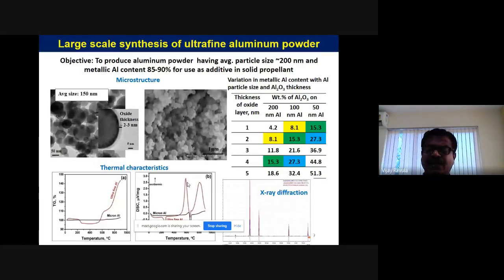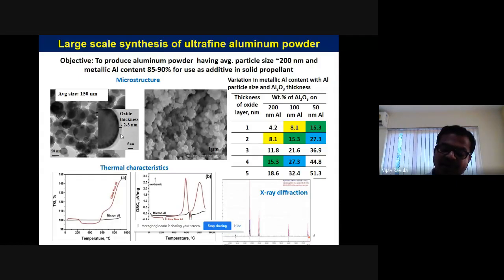So in order to improve the shelf life of the material, what we have done is, on the particles, we grew an oxide layer. It's very thin. The beauty of aluminum is, once an alumina layer forms, it doesn't allow the oxygen to diffuse further. It acts as a barrier for oxygen going into the material. But the problem is, if the thickness is more, they don't burn. Alumina itself acts as a resistance to the oxidation of the metal. So you need a very small thickness, so that the material will not get oxidized when it is kept exposed to the air.